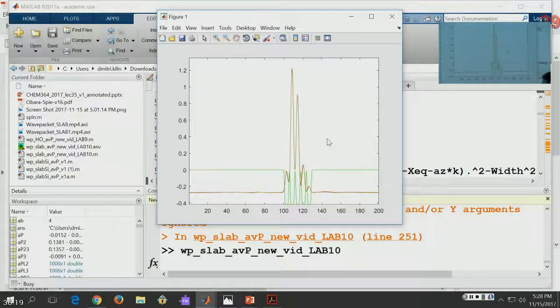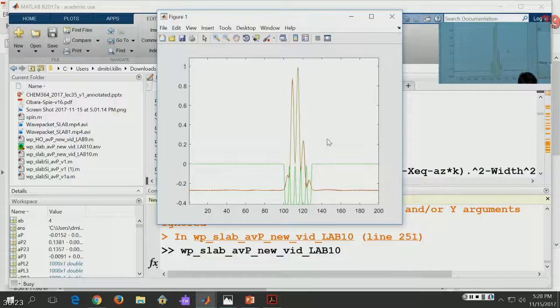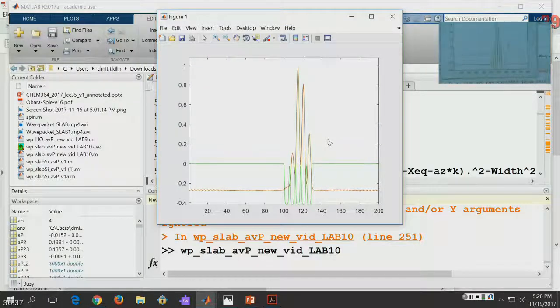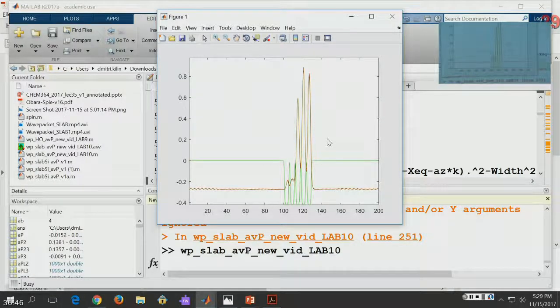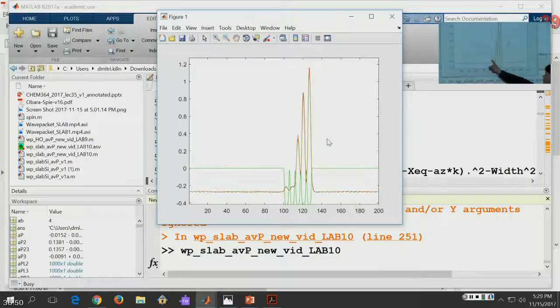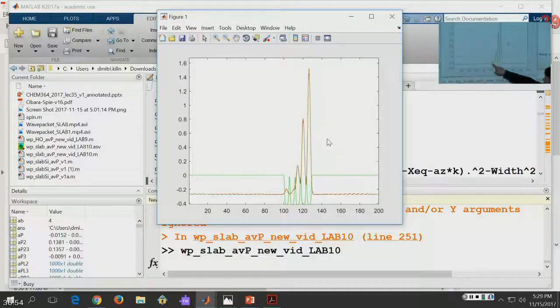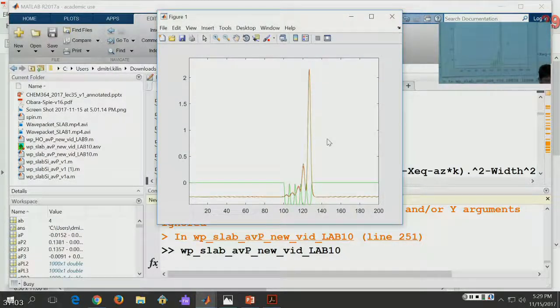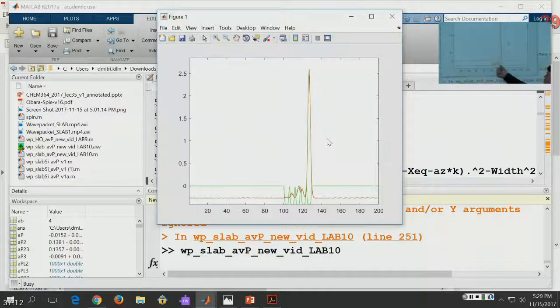And in fact, if we are describing solids, like metals or semiconductors in an excited state, the electrons are, in chemical language, in hybridized molecular orbitals. So the electron is delocalized over multiple atoms. Here we started at the leftmost, and then as time passes, we see that the electron distribution prefers to stay at the atomic centers, but it is allowed to distribute across several atoms, and the center of this wave packet moves from left to right. Probably if you wait long enough, it may reflect back, like an electron inside the thin film.